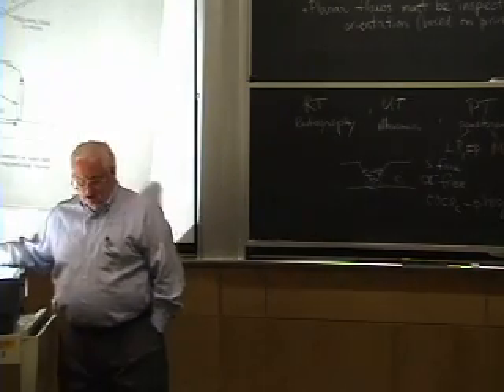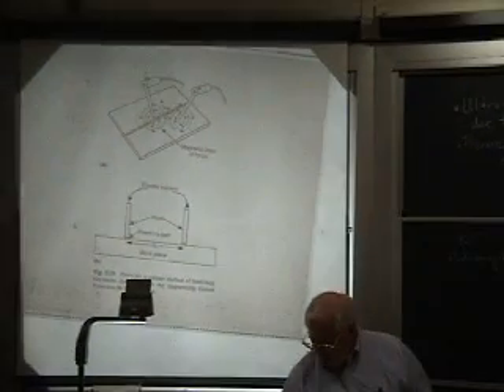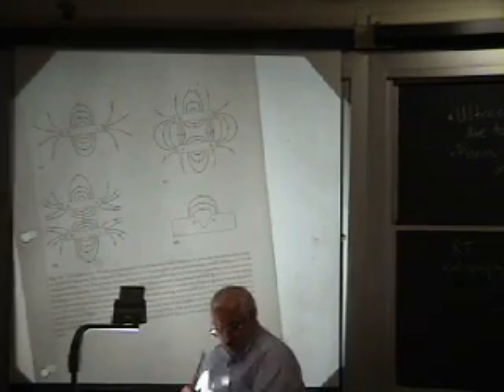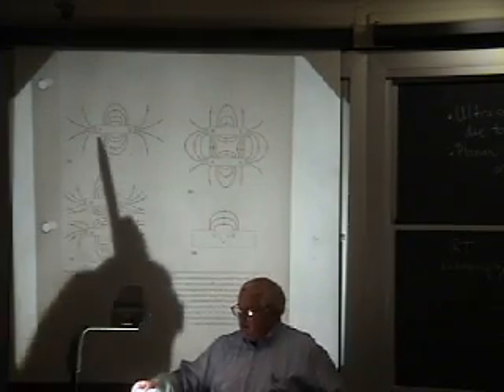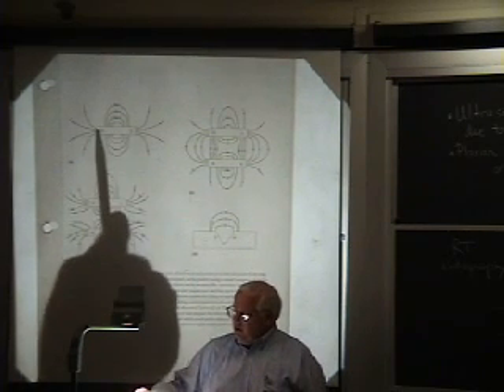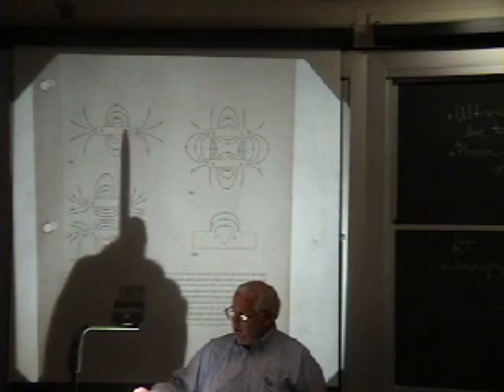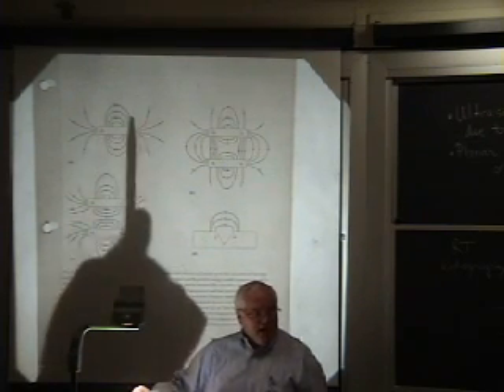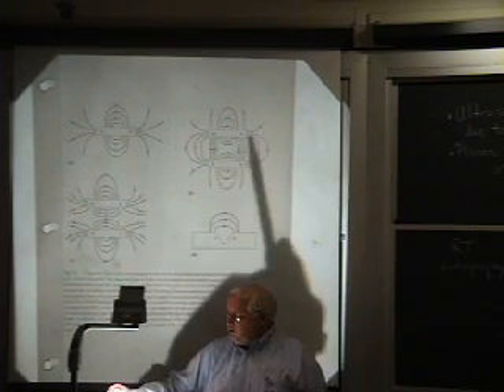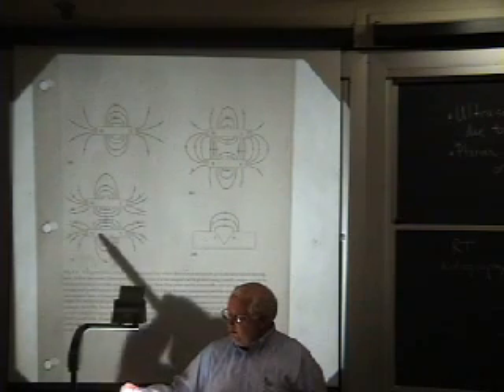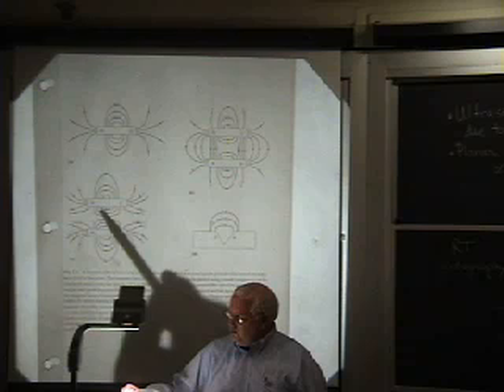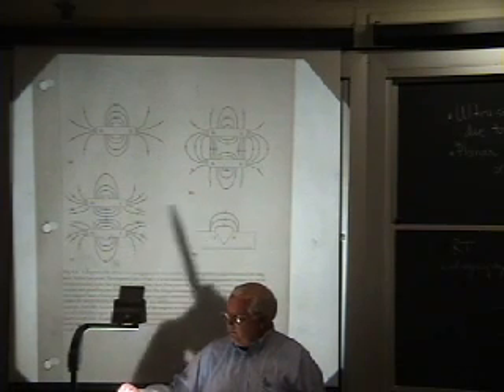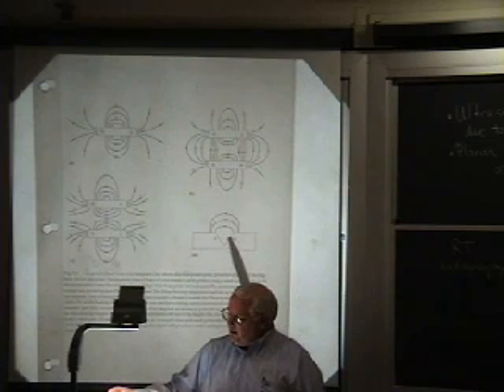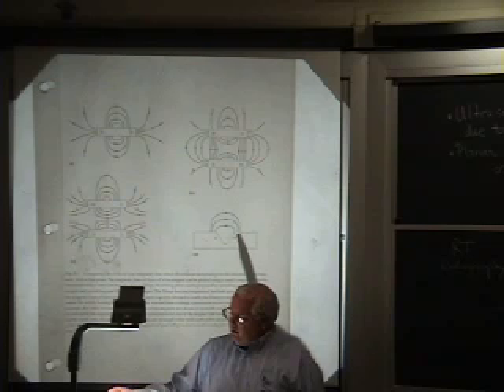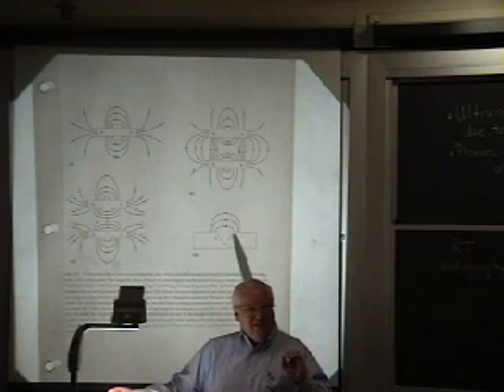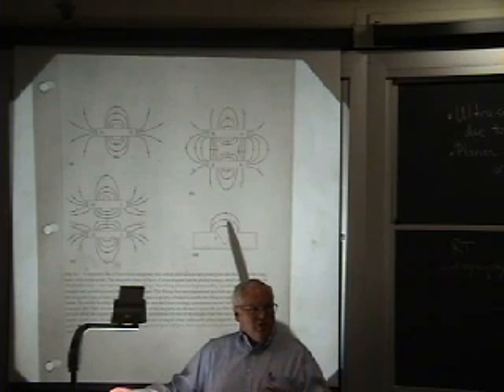Okay, magnetic testing, on the other hand. There's lots of ways to magnetize something that's ferromagnetic. Let's start with this one before we go to that. Anything that's ferromagnetic has a north pole and a south pole, and there are flux lines that go around that. If you ever played with iron filings and a magnet, that's basically what you're seeing, the flux lines. If you have two of these, then you have a more complex flux field. If you align the poles so that they're repelling, you'll have a different set of things. But if I magnetize something that has a notch or a crack, I will get a north and south pole, and in a ferromagnetic material you have the potential to have about 10 times the magnetic field density as you do in the air surrounding it.